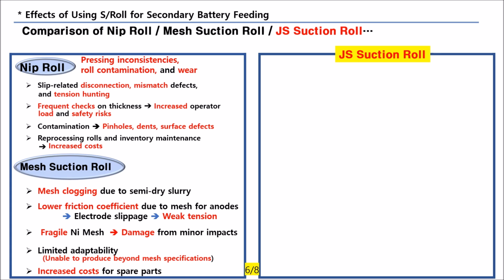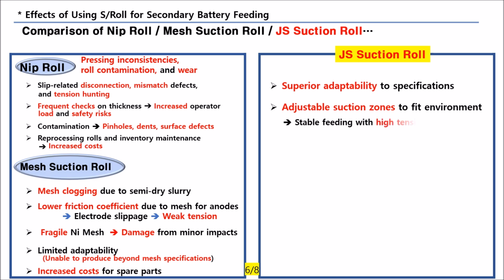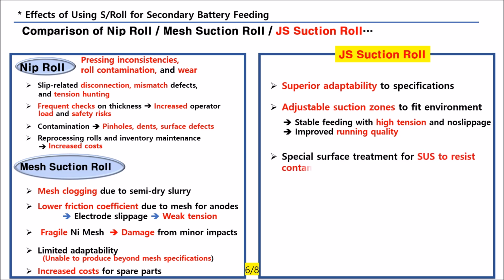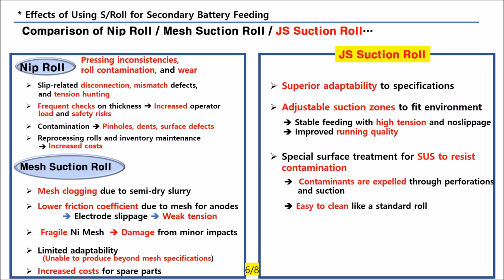In contrast, our suction roll features an integrated design without separate inner and outer tubes, allowing it to accommodate a wide range of customer-specified dimensions. The suction zones can be adjusted to fit the roll path, ensuring stable feeding with excellent tension and slip-free operation, thereby enhancing running quality. Defects such as tension hunting and wrinkling are minimized, as the electrode contact surface is made of SUS perforated mesh with a special coating that resists contamination. Specifically, contaminants are expelled externally through the perforated mesh and suction system. This design not only makes cleaning as easy as with a standard guide roll, but also minimizes surface damage, making it a highly durable, near-permanent product.